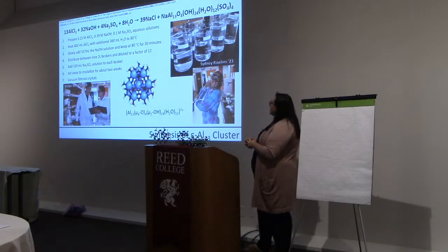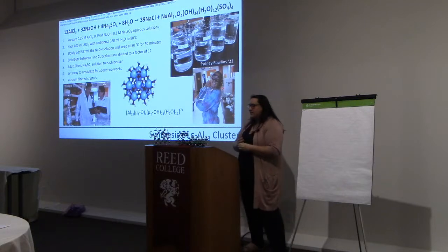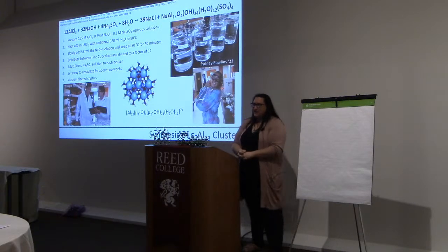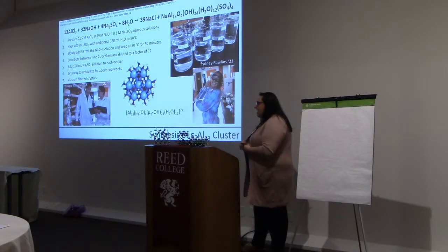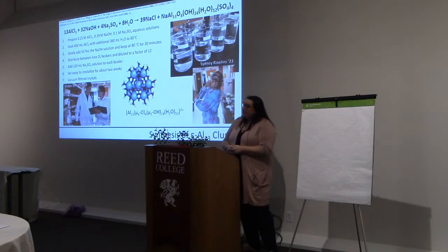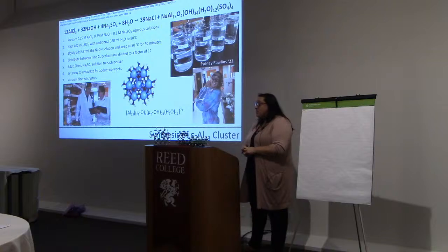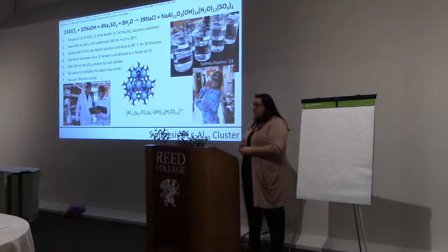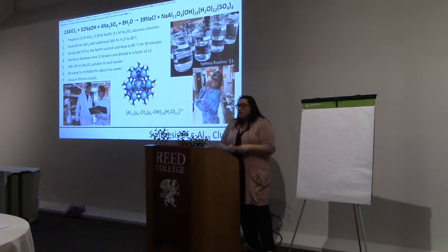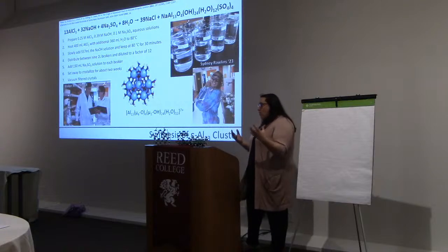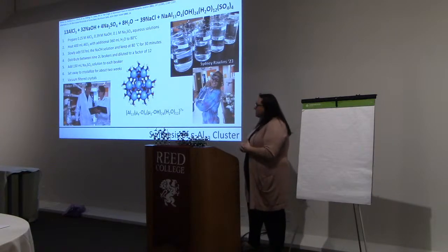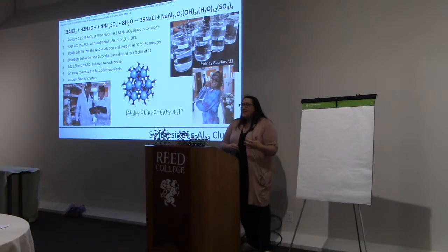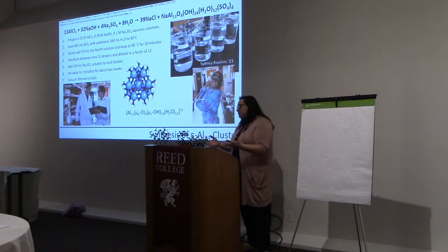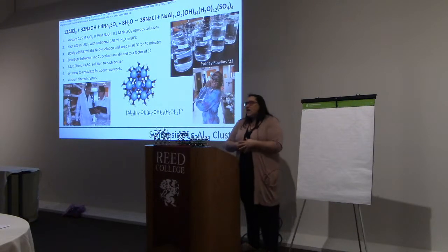Here are some of my students, and the first one we decided to synthesize is the easiest of the clusters to synthesize, and that's this epsilon Keggin. So we essentially just dissolve salt in water and adjust the pH. So they take aluminum chloride, they heat it in water to 80 degrees Celsius. They slowly add sodium hydroxide so it doesn't precipitate out too quickly. They let that stir. They dilute it